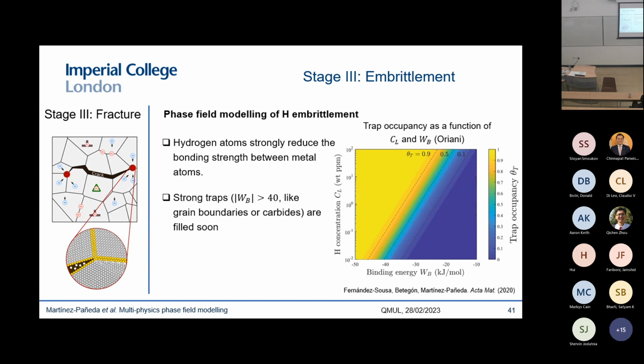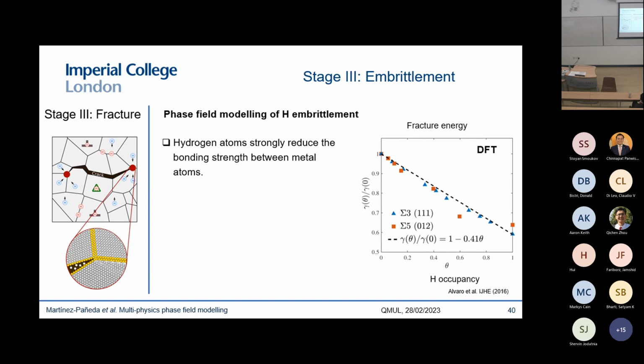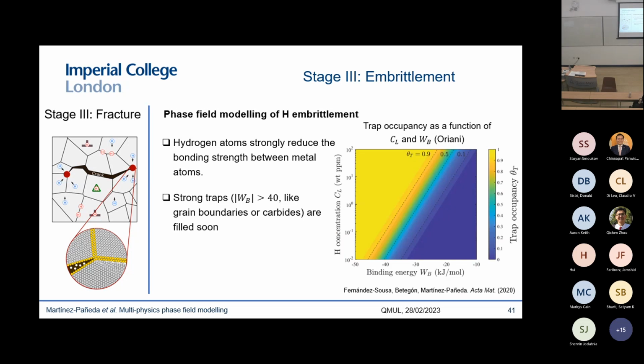The second thing to consider is that, okay, so this is the first ingredient, and this is quite important. However, you may wonder how much hydrogen is in our grain boundaries, right? Because if we are somewhere on this side of the graph, then we're not going to have a lot of hydrogen, and the reduction is going to be small. So the next question is, how much hydrogen do we have in our grain boundaries? And the answer to that comes from the trapping thermodynamics. You can use Oriani's equilibrium to relate the trap binding energy to the hydrogen lattice concentration and the trap occupancy. And the trap binding energy is a material property that we can measure in our labs, and it tells us how energetically favorable it is for the hydrogen to go to that particular microstructural feature. And grain boundaries are strong traps. We measure in our labs something on the order of minus 40 kilojoules per mole. So you can see that with very little hydrogen content, as little as 1 part per million, our grain boundaries are effectively going to be almost full. So it is very energetically favorable for the hydrogen to sit in grain boundaries.